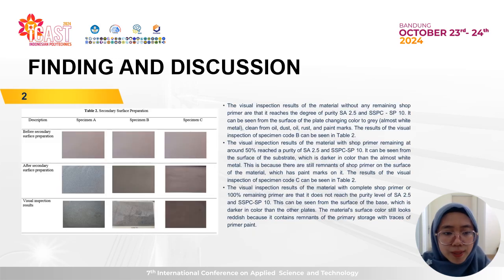And look at the picture. This is the visual inspection result. The visual inspection result of the material without any remaining shop primer reached the degree of purity Sa 2.5 and SSPC SP10. It can be seen from the surface of the plate changing color to gray, almost white metal, and clean from oil, dust, rust, and paint marks. The result of the visual inspection of specimen code A can be seen in table 2. And there is a picture of before secondary surface preparation and after secondary surface preparation, and the visual inspection result.